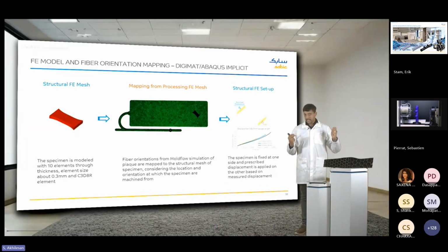Now, we have done tensile testing with a certain specimen geometry. We take the same specimen geometry and then we use a structured mapped mesh in the FE solver to create a structural FE mesh. And using tools such as Digimat-MAP, we can then align the fibers in the specimen in the same orientation as in the real part, similar to how we have cut them. And then we do it at 0 degree, let's say at 45 degree and 90 degree. We create the same orientations in this mapping and map the fiber orientation from the molding or the simulation mesh to the structural mesh. Now this mapping is completed. You have the fiber orientations in the specimen geometry.